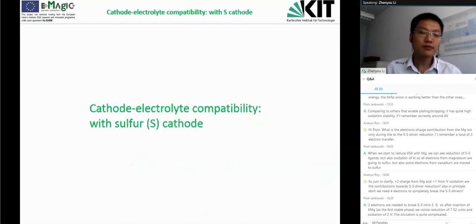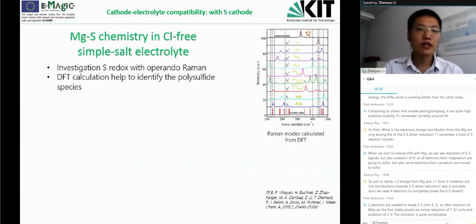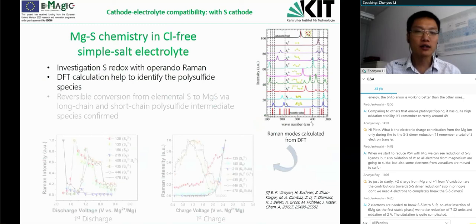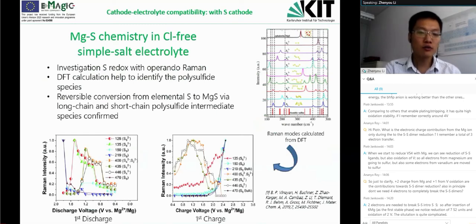And the last example, or the compatibility test, is with the high capacity sulfur cathode. So in this section, we have investigated the sulfur redox by using this borate electrolyte, and we used operando Raman technology, and also correlated the Raman modes with different polysulfide species with the help of DFT calculation. And this results in these two graphs. So basically we have the evolution of different polysulfide species during the charge and discharge process.